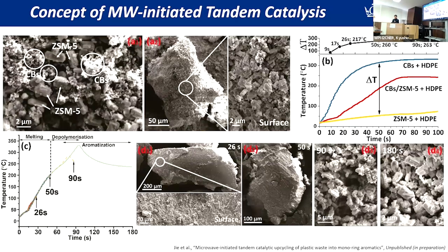This is, I think, a very exciting and powerful characterization. If you look at the very left-hand side, that is the bare fresh catalyst composed of carbon black and the zeolite. And when we loaded this, the part in the middle, this big chunk, is the plastic piece, and all these small particles are actually dispersed on the surface. If we zoom into that, you will see the catalyst, these tandem catalysts, let's call them that.